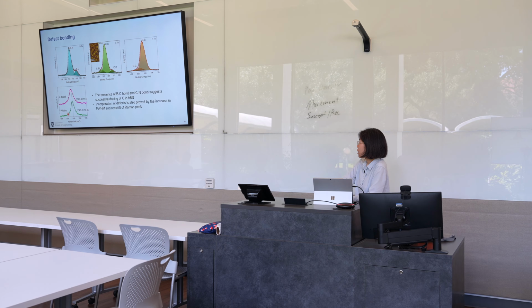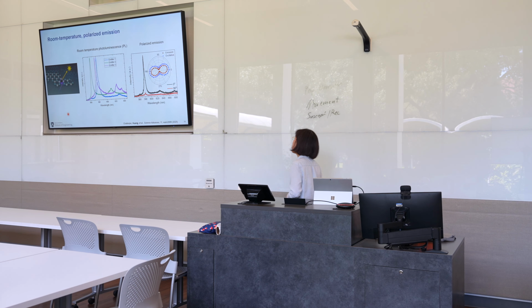So next, let's look at the optical emission property. Eventually, we want to look for single photon emitters in these materials. At room temperature, if we measure the photoluminescence spectrum, we can see some very sharp and bright peaks coming out. These apparently are from the carbon defects, because pristine boron nitride has a very large band gap in the UV range. In addition, we realize these emissions are polarized in plane. That means there is an in-plane dipole moment for these emitters. So we have these bright emissions. We want to confirm if these are single photon emitters.